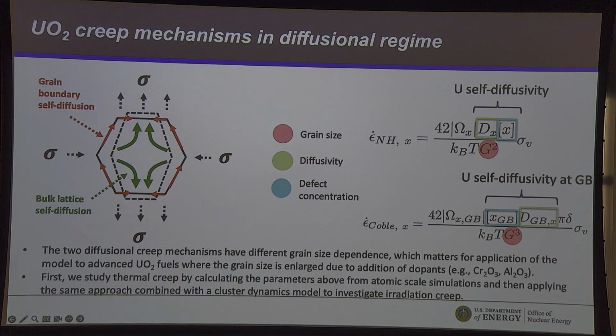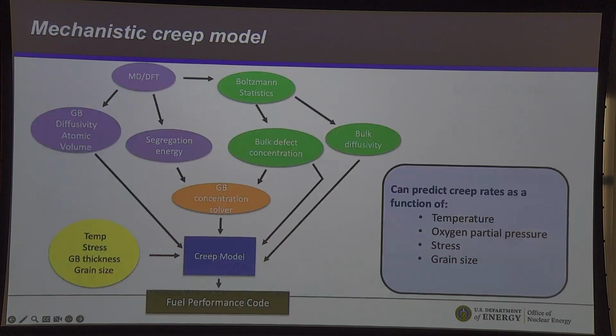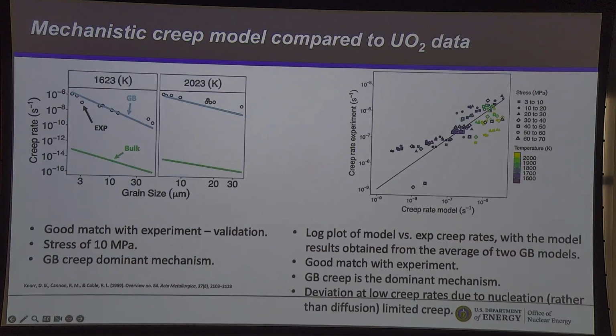And that matters because the grain size for the first one scales with a square and the other with a cube. So if you made your grain a lot larger, let's say by a factor of 10 larger, whether that creep rate scales with the square or the cube, that's going to give you a different result. So we built, using the kind of defect tools that I showed, a workflow that can assess that. And that workflow can eventually be put into a fuel performance code. I'm not going to show you any of how that workflow functions, but we're happy to answer questions on that later.